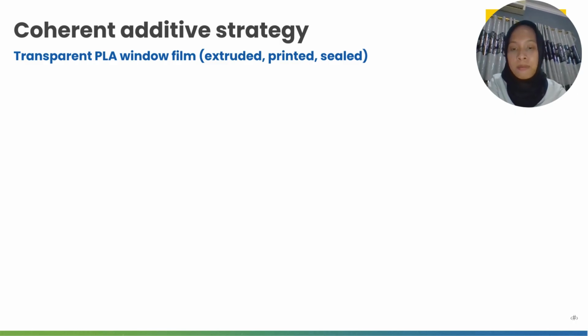And the last one is film H, or ESD plus shelf life first, which is the most robust optics plus ESD durability. The additive package types is AO plus UVA plus HALS, carefully haze screening, and a clear ESD coating tuned to reach the dissipative range. And it has the best optical stability plus ESD reliability for electronics. The downside is higher risk for compost mineralization or certification. Coating chemistry must be validated.